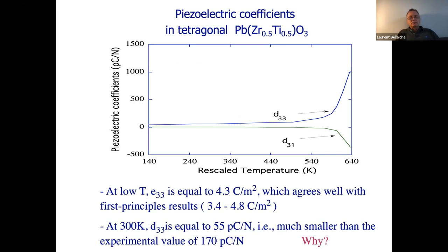And they say, okay, so this is good to find the monoclinic state. What about piezoelectricity? Because PZT is super important for piezoelectricity. So with the effective Hamiltonian, we can calculate the piezoelectric coefficient. We get d31, d33. d33, for instance, is you apply an electric field along z, and you look at the strain along z. So if you look at d33, let's say at room temperature, this effective Hamiltonian is telling you it's 55 picocoulomb per Newton. But experimentally, it's 170. So something was very strange.